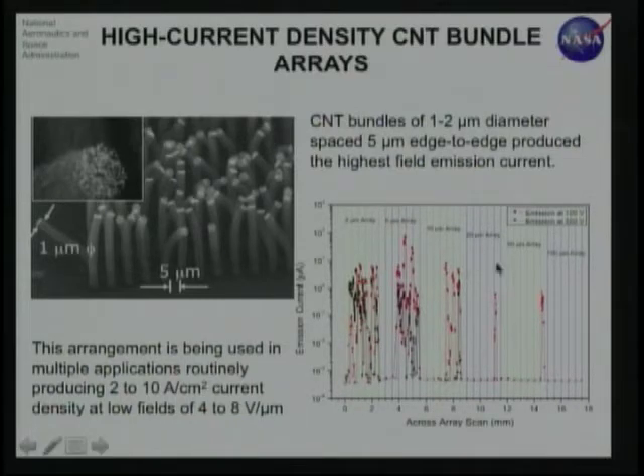And that's what this graph shows here. When you scan a microprobe across for the same potential, you'll notice that at one particular number, the current emission is almost an order of magnitude higher than anywhere else. That turns out to be this combination: between 1 and 2 microns diameter field emission bundles, which are spaced about 5 microns from each other. And they produce quite high current.